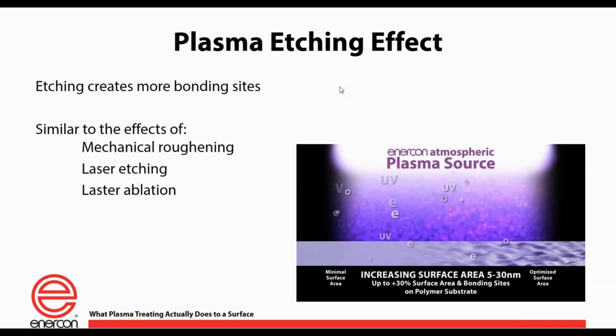All right, so then after the cleaning step, or basically at the same time that the cleaning step is taking place, we're also etching the surface. This is the manufactured surface that you're looking at in the bottom right-hand corner, but there are also natural surfaces that we treat from time to time, and you get a completely different look to that surface. It's much more jagged if you were to look at it under an electron microscope. But basically what happens then is you do the same thing. You are eliminating some of those peaks and valleys, and you would think that those peaks and valleys would actually increase the surface area, and they do. The problem is you're looking at it at such a small level that the adhesive or the paint or the bond can't actually get down to the surface. So whether you're looking at a manufactured surface or a natural surface, this etching effect increases the overall usable surface area.